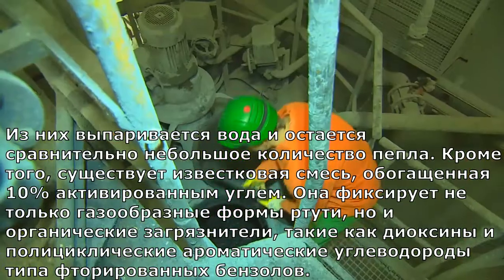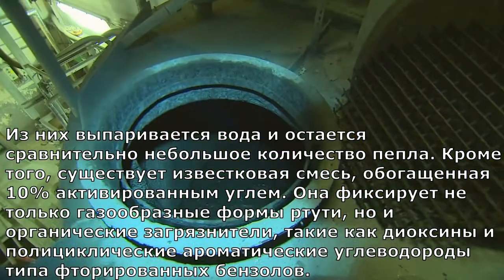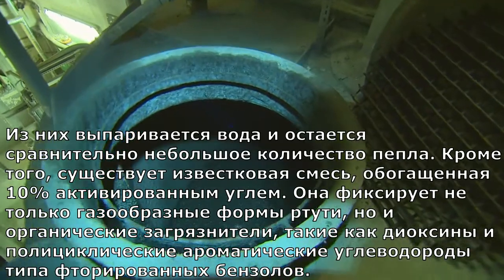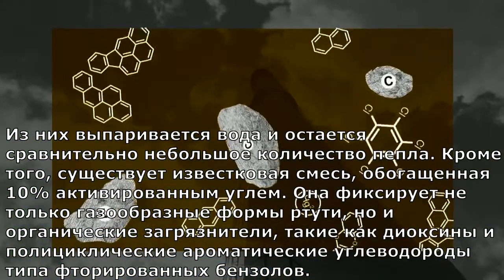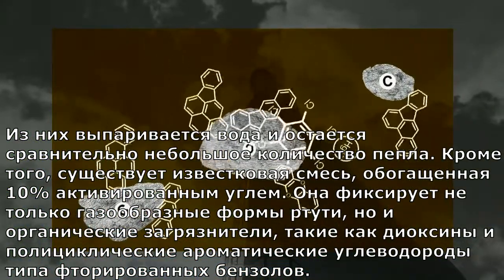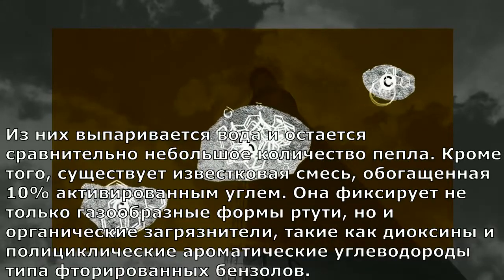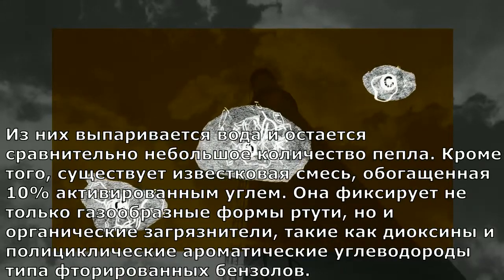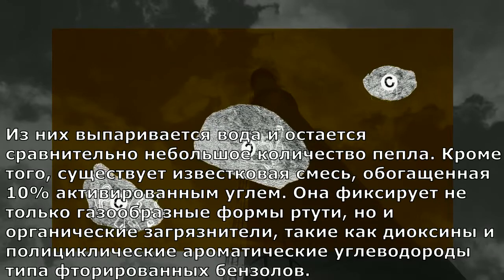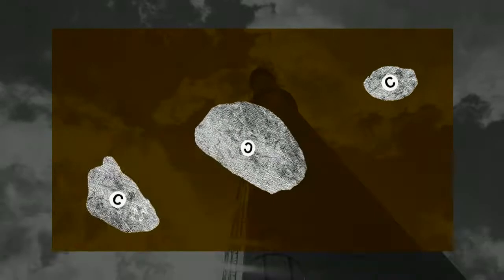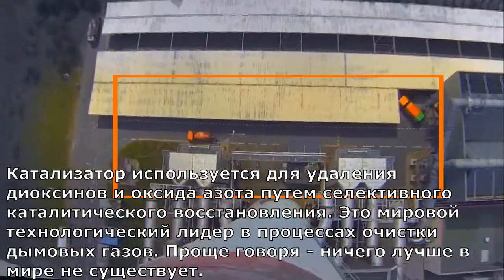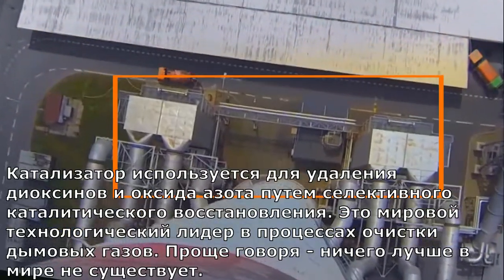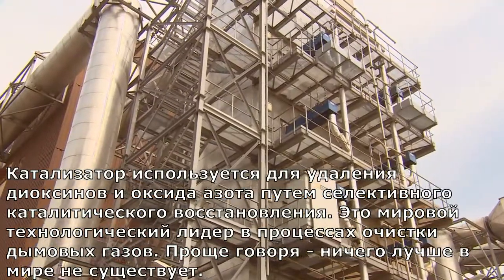In addition, there is a scrubbing lime slurry enriched with 10% active carbon. It captures not only the gaseous forms of mercury, but also organic pollutants such as dioxins and polycyclic aromatic hydrocarbons of the type of chlorinated benzenes. The catalyst is used to remove dioxins and nitrogen oxides by selective catalytic reduction.